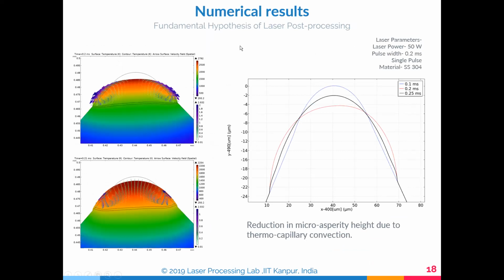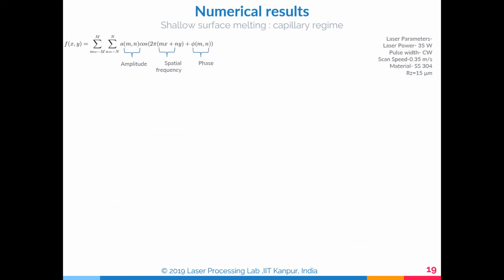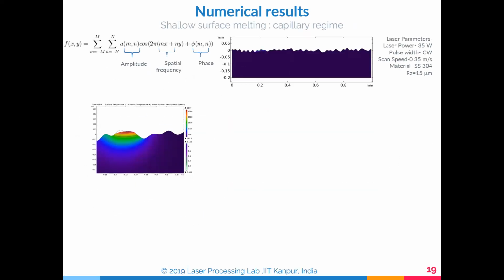So the fundamental hypothesis of laser post-processing is, we try to heat the surface and do the melting of the surface. It was trying to move here and there. And then we have the reduction in the asperities height due to thermocapillary actions which we were looking at. So then these are some of the shallow surface melts which were done and the capillary actions which we did.